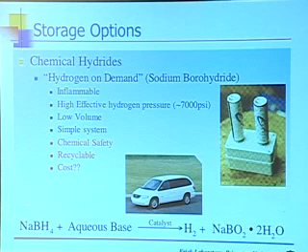So what we're talking about is if you take sodium borohydride and you just put it into water, you start to bubble out hydrogen. But if you put it in strongly basic aqueous solution, say 2 to 10 molar sodium hydroxide, it is indefinitely stable. It'll sit there on the shelf forever as sodium borohydride. And if you then have a catalyst that you can pass this solution over that will strip out the hydrogen, you have a nice way of storing hydrogen.